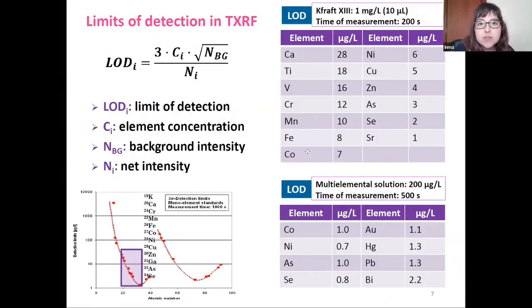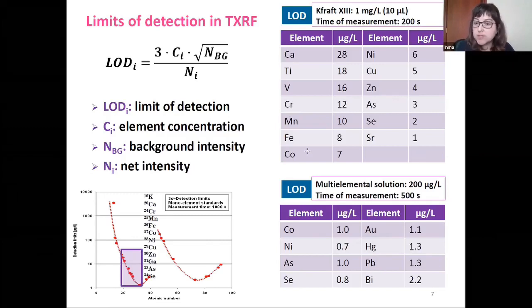In TXRF, the limits of detection are calculated according to this formula, using the concentration of the element, the background intensity, and the net intensity of the selected elements in the spectra. This figure typically represents the limits of detection achieved by TXRF according to the atomic number. In the tables on the right, we calculate the limits of detection for certain elements using multi-elemental standard solution. As we can see in the second table, the limits of detection can vary from 0.7 to 2.2 micrograms per liter.